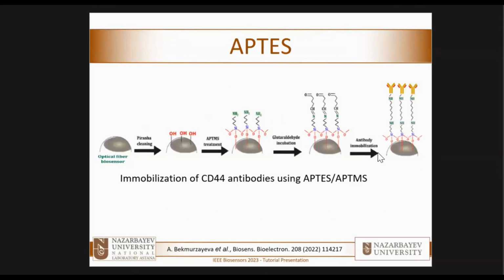The other way that we can use is silanization. So to silanize the fiber, basically using silane groups. That is a quite typical functionalization, for example, in some medical devices based on stainless steel that are not meant for detection, but rather are meant to extract specific cell samples, particularly in recirculating cell problems. In this case, APTES is based on usually cleaning the surface of the biosensor and performing a treatment with this sort of biological glue that allows the bioreceptor to stick very well. In general, there is an incubation in glutaraldehyde, GA, and then the immobilization of the antibodies. The surface treated with APTES or APTMS with the excessive silane group is actually a good method for the immobilization of bioreceptors and then further the detection.